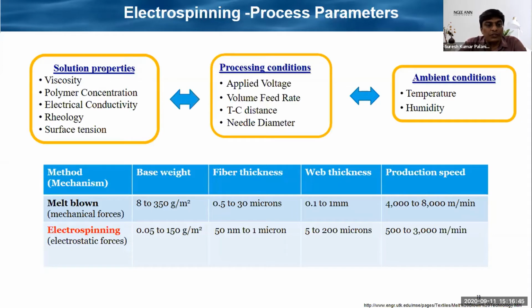When we compare melt blown and electrospinning, we can clearly see electrospinning has a fiber thickness of around 50 nanometer to 1 micrometer, compared to melt blown at around 0.5 to 30 microns. The web thickness is around 5 micron to 200 micron, whereas in melt blown it is around 0.1 to 1 millimeter. The productivity range of melt blown is around 4,000 to 8,000 meter per minute, whereas electrospinning is around 500 to 3,000 meter per minute.